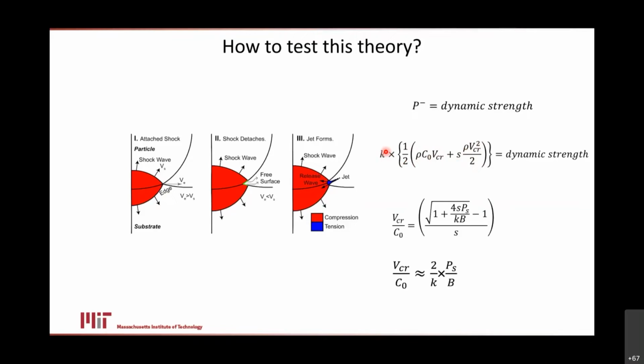You rearrange this equation, you keep only a physical root, and you've got a very simple scaling law. If indeed jetting is a hydrodynamic phenomenon, then the velocity at which we see jetting set on will be a function of the speed of sound and the bulk modulus, so elastic properties. And of course, we have to exceed the local strength, which, by the way, you might approximate with a measurement of spall strength. So the dynamic yield strength goes in on the top, and the elastic properties here on the bottom.